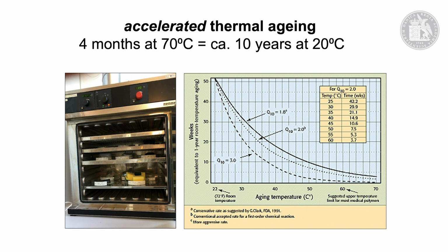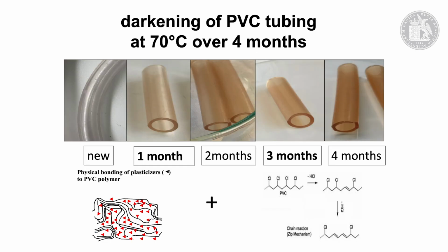So we've done some accelerated thermal aging to try and compare accelerated aging and real-time aging. And we can see that after a very short time, we're getting degradation of most of the plastics. This is an example of PVC, and you can see it's beginning to look a bit like the Apollo spacesuits already after a few months. So it's extreme.